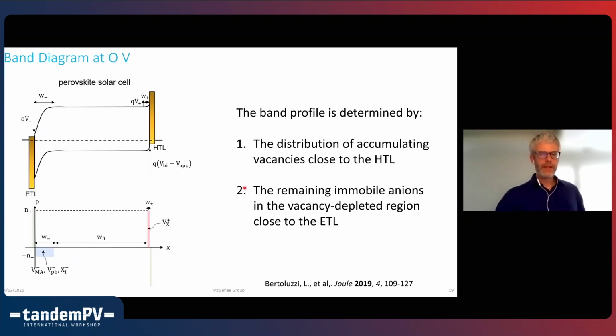And let me walk you through the band diagram. We'll start with one at 0 volts, and we see that the energy bands are flat through most of the solar cell, precisely because the mobile ions have moved. I like to look at where the charge density is, and outside the cell we have some charge in the electrodes that normally would set up a built-in electric field, but then the vacancies move, and that leaves some space charge on this side and piles charge up on the other, and that internal charge cancels the built-in field in most of the device, and so almost all of the band bending is on the left near the electron transport layer.